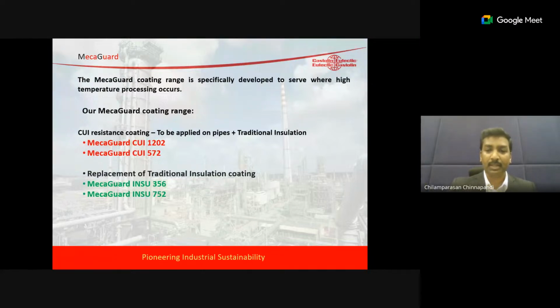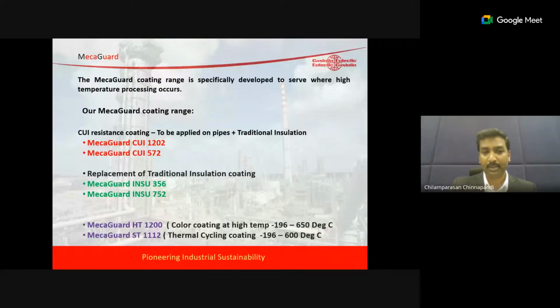At the same time, this is a brushable coating, and it can completely avoid any corrosion and avoid traditional insulations. And we have a thermal shock coating also, for problems on pipes where the temperature goes up and down because of thermal cycling. It can work from minus 196 to plus 600 degrees. If you're getting corrosion because of thermal shock, we have a coating.